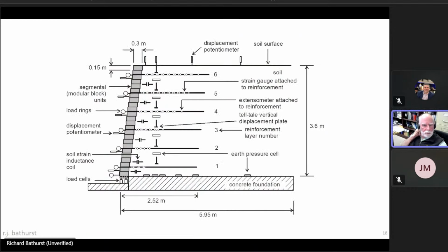And here's a cross section of typical instrumentation for these walls. So you can see that there were strain gauges and extensometers on the reinforcement. There were settlement gauges, and there were displacement gauges at the front of the wall to measure outward displacements. The contact loads were measured directly. We measured the vertical and horizontal toe loads at the footing and the earth pressures at the bottom of the backfill soil. And in fact, there were over 300 pieces of instrumentation in a typical wall. And some of my friends used to tease me and tell me that I was testing an instrumentation reinforced soil wall.